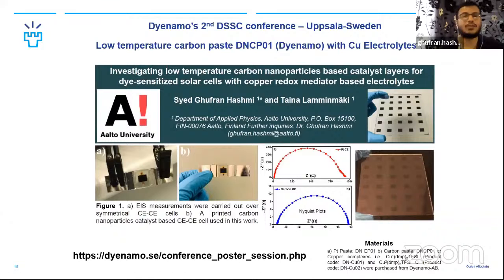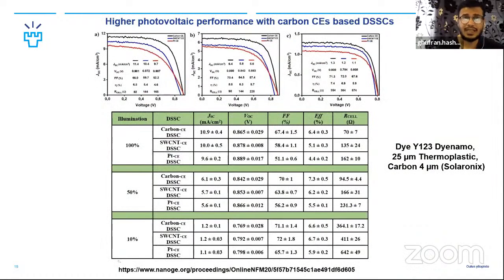So again it was very reproducible results, where the carbonaceous composite catalyst material, you can see all the details with this paste code. But this paste of carbon is a low temperature screen printable paste, and that again outperformed in the electrochemical characterization compared to the screen printed platinum catalyst based counter electrodes. So then